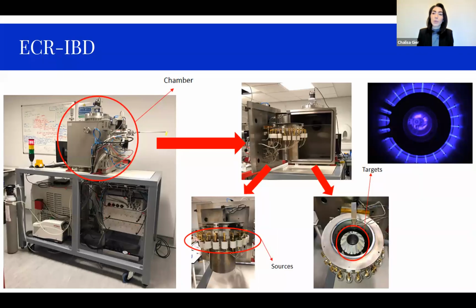And here is our newest ECR ion beam deposition system. This system has 24 ion beams with conical targets, and it was developed in collaboration with Polygon Physics. With this system, it provides the flexibility to fabricate mixed material coatings with differing percentages, as we can control the beam property individually using LabVIEW.